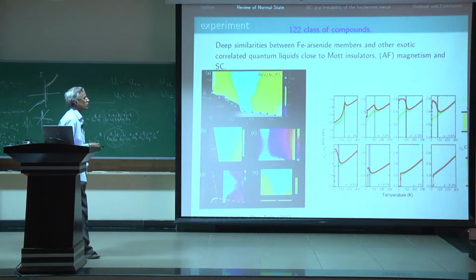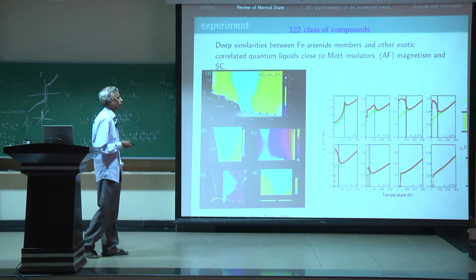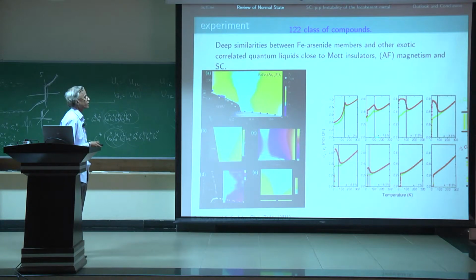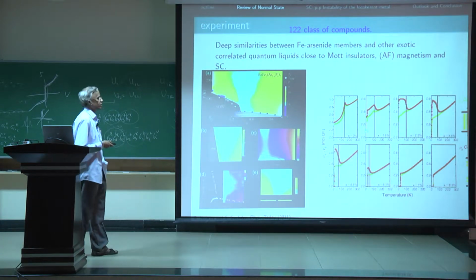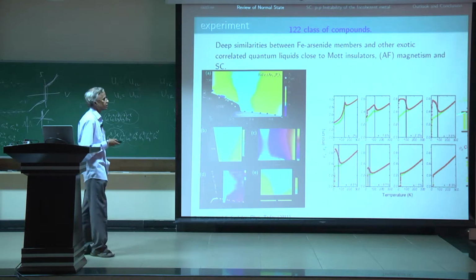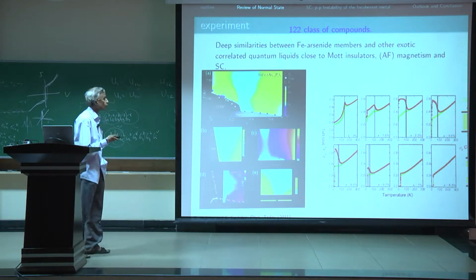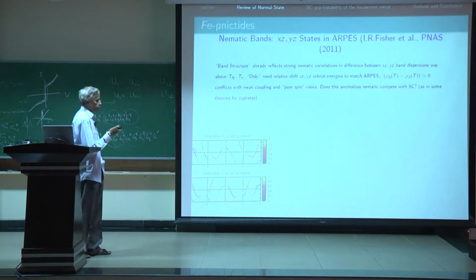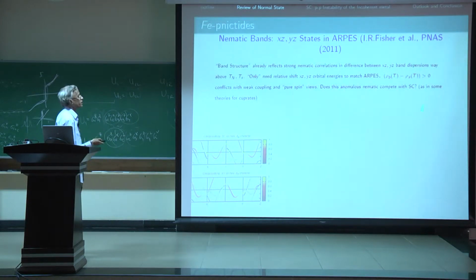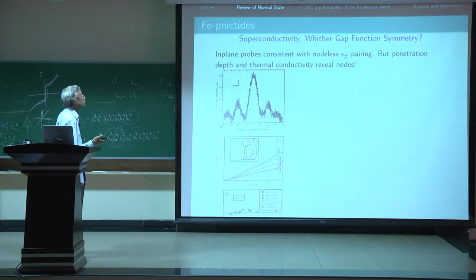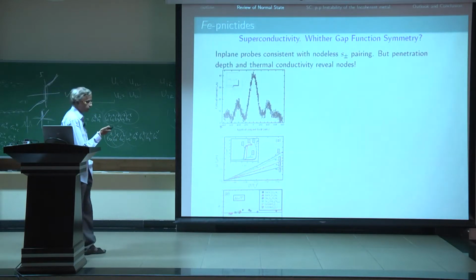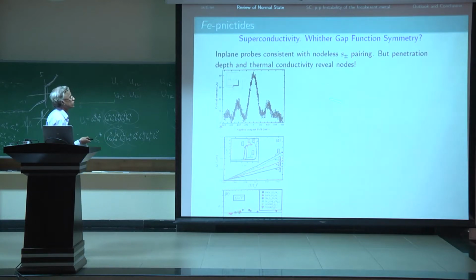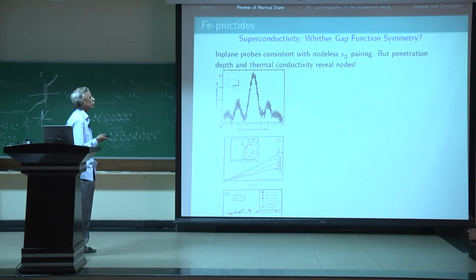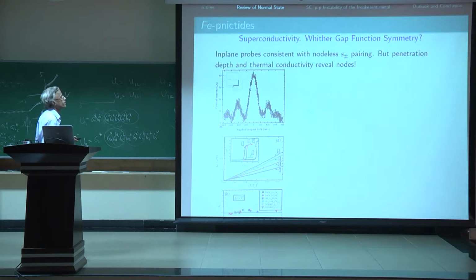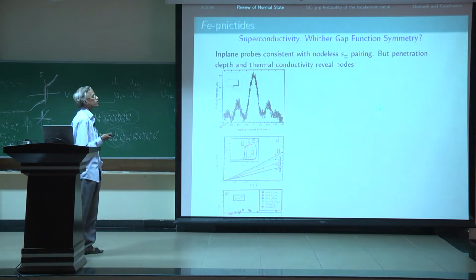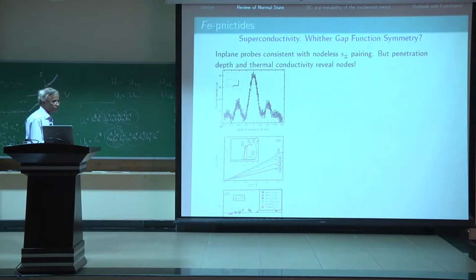So the question is, does this hide a kind of criticality associated with the spontaneous breaking of the discrete rotational symmetry of the square lattice? And what is its connection to superconductivity? How may this arise from a normal state, and so on? There is independent ARPES data from the Fisher group, which basically shows that the band structure itself is anisotropically renormalized even above the structural transition. There is additional evidence for an electronic state, which one may dub an Ising nematic state.